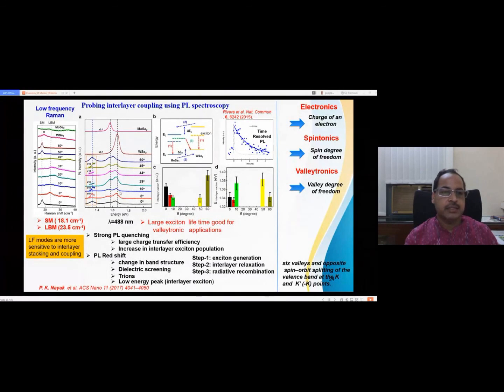Why is there a shift? There is some trion formation, and other higher order complexes. In addition to the exciton, some extra electron is added, and that is called the trion peak. That's why there is a change in the band gap. Another is the low energy peak, where we can see the interlayer exciton. So close to 0 and 60 it has been plotted as it is, and in the case of 10 degree and close to 60 degree, you can see we have multiplied by a factor of 10. Here it has been extrapolated.